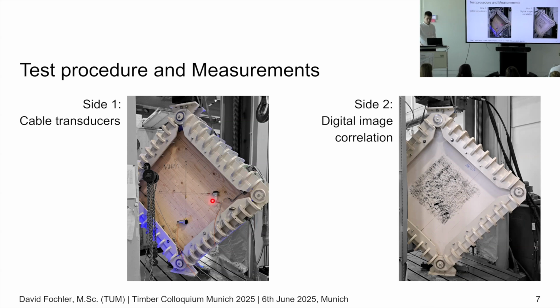Side 1 had 2 cable displacement transducers, one in active and one in passive direction of the vertical compression load. And on the second side, the measured area was captured with a digital image correlation system. That is why we used those white surfaces with black points on them.